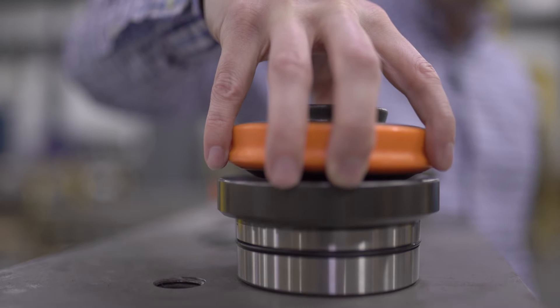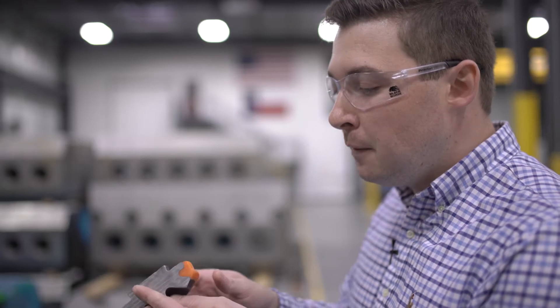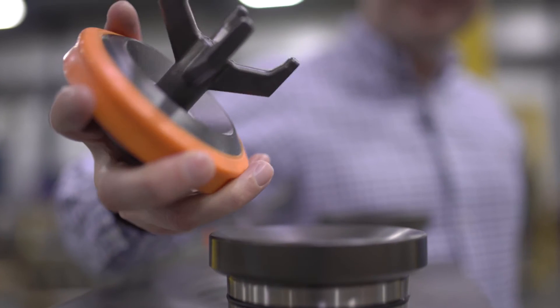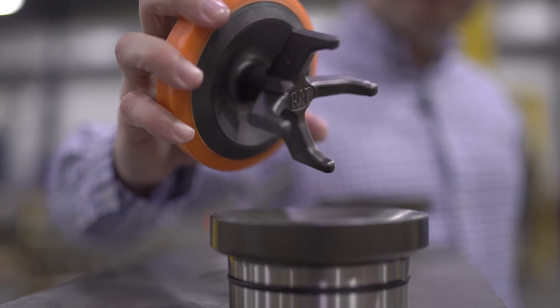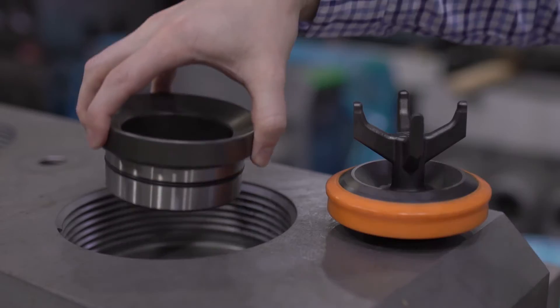Starting with the valve, we utilized a bonded and overmolded urethane to help mitigate abrasion failures and detachment of urethane during operation. Furthermore, we increased the metal contact surface area to help mitigate impact damage during operation.